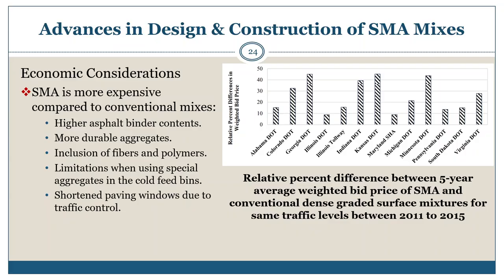This slide summarizes some of the unit bid prices, which affects the cost effectiveness of different mixes for SMA mixtures in terms of the percent higher unit cost in comparison to conventional dense graded mixes for selected agencies. The reason for the higher unit bid prices is related to the material requirements that were previously mentioned on the previous slide, as well as on this slide, and the amount of asphalt binder added to SMA mixtures.